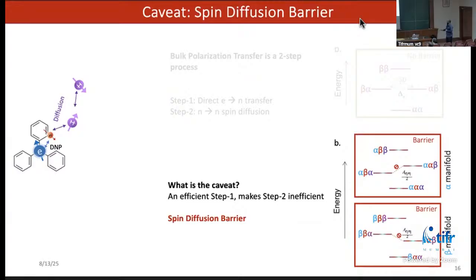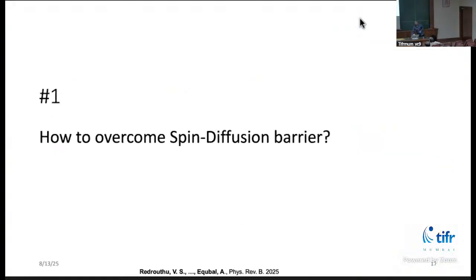This problem is well understood as the spin diffusion barrier. It can be understood in a way that spin diffusion happens between two homonuclei. If two nuclei are similar, they have similar energy level, they can flip-flop. The energy is conserved if there is flip-flop. But because one nucleus is strongly coupled to the electron than the other one, the degeneracy is lifted. They are no longer homonuclei. And this causes a diffusion barrier. So in order to make the bulk DNP process efficient, one has to overcome the spin diffusion barrier.